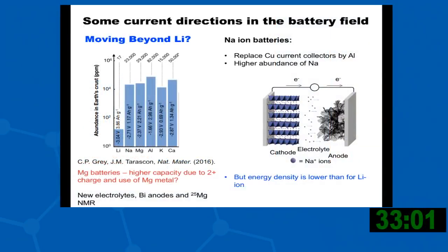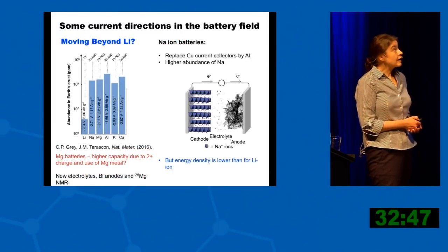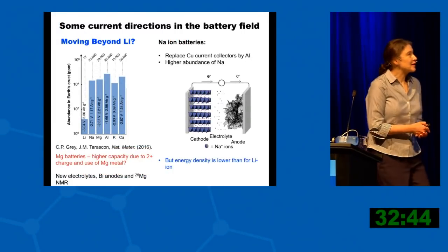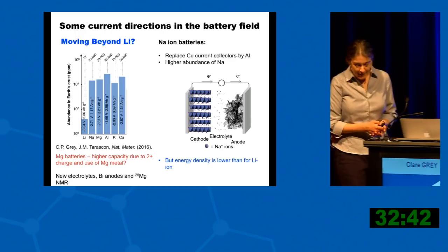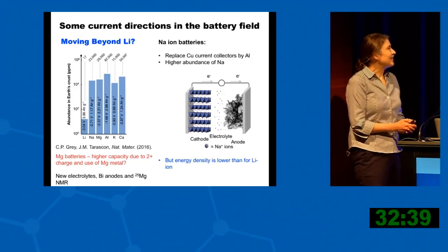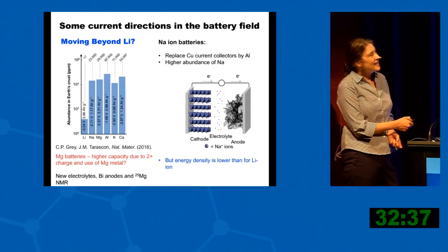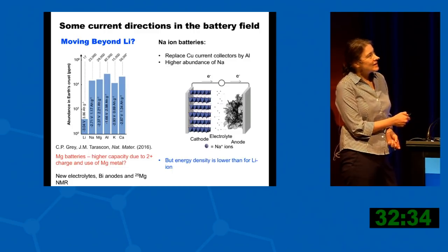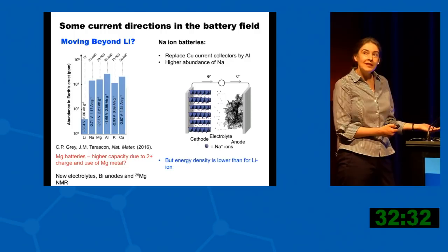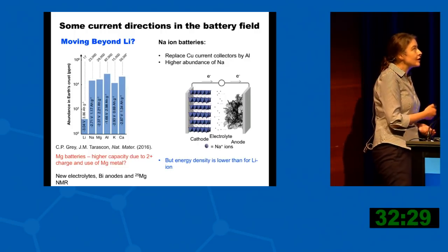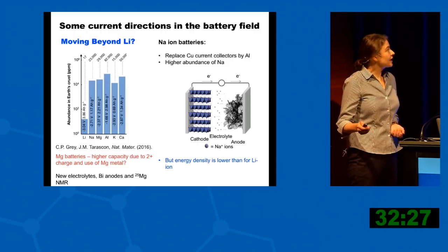Then we can think about moving beyond lithium to other elements such as sodium. One of the nice things about sodium is that you can use a much more abundant element, but also you can replace the copper current collector with aluminium. If you put an aluminium current collector with lithium, you form a lithium aluminide, which you don't form with sodium. So that's another reason for reducing cost.